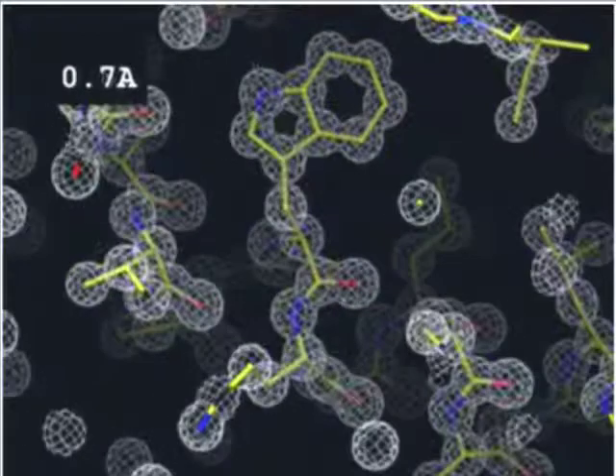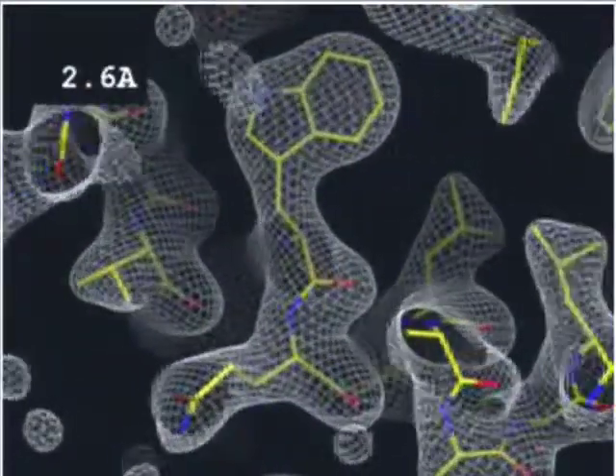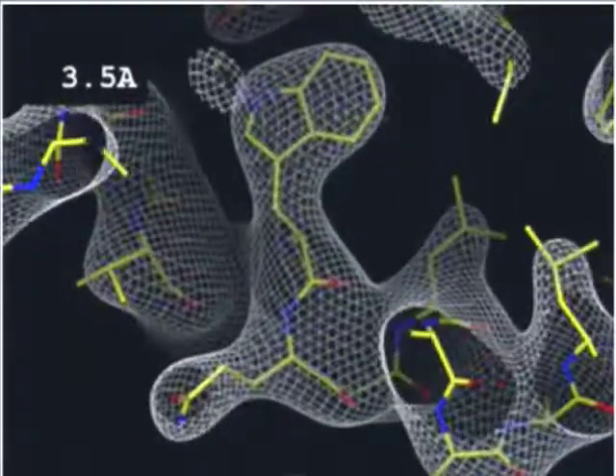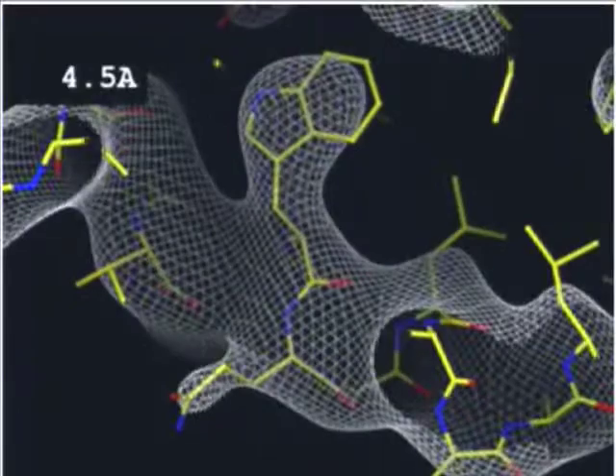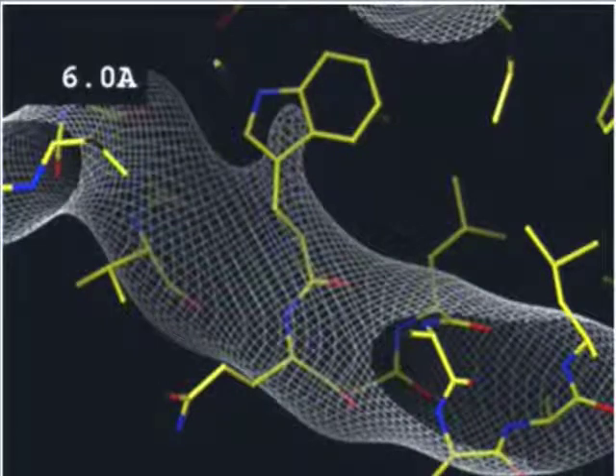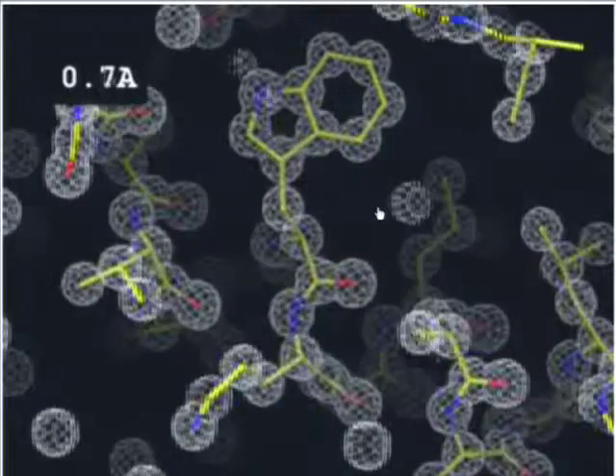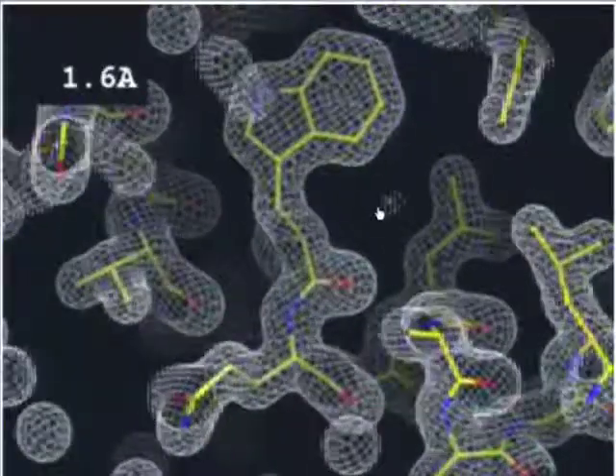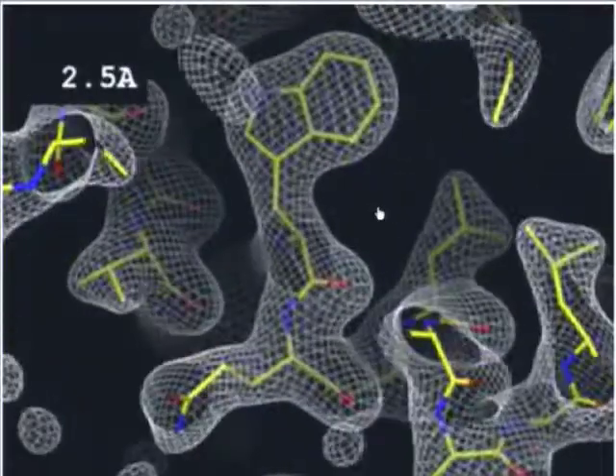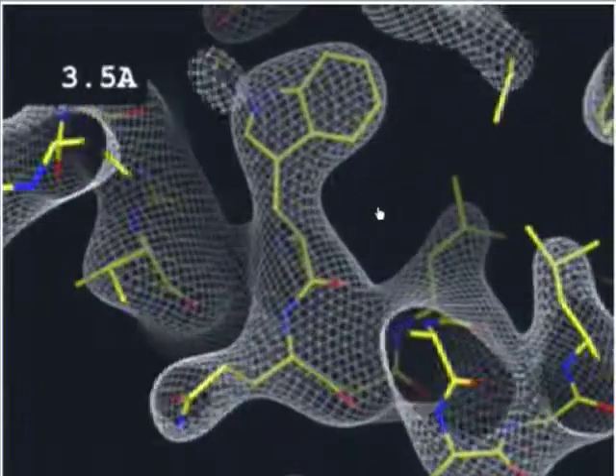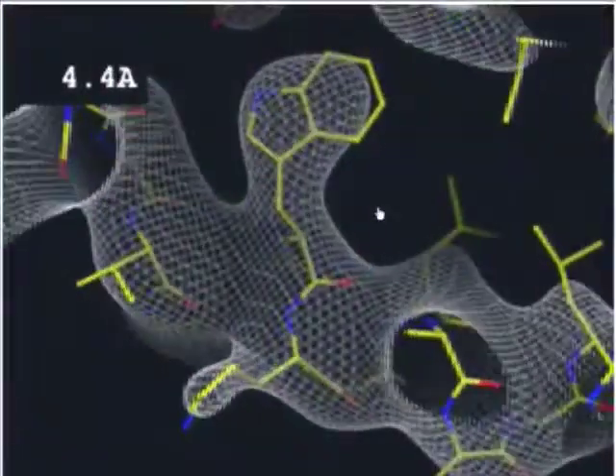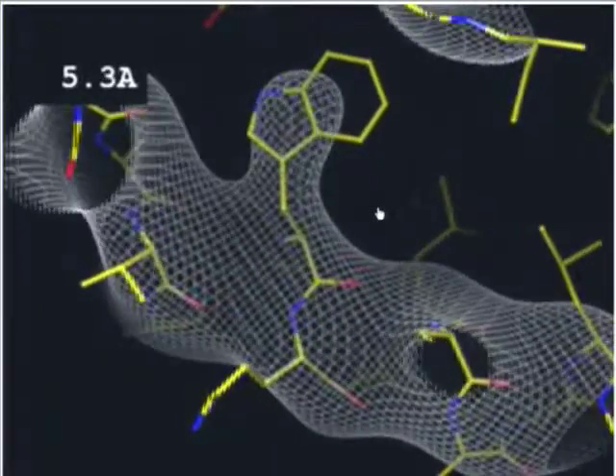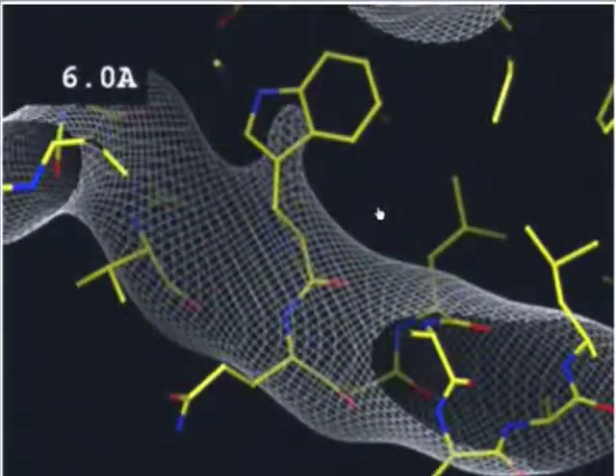However, the resolution depends on the data and the crystal, and as the resolution goes down, we start losing information from the electron density, so we start losing the positions of the side chains, and here is the resolution. At 6 angstroms, we can see just the shape of the molecule, we cannot see all the details, whereas when this video started, at 0.7, we can really nicely see the aromatic rings of the side chains of three amino acids, which have aromatic rings, which are tryptophan, tyrosine, phenylalanine. These are the first thing which we look in a map because they are the easiest to identify.